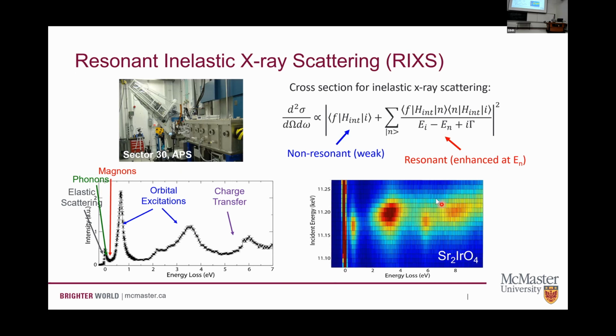Yeah, so that's the orbital selectivity that I mentioned. The difference here in energy along the vertical, which is as we're scanning the incident energy, that's 10 Dq. That's the difference between exciting your core electrons into the t2g levels, that's what you're getting here and here, versus going into the eg levels, that's what you're getting here and here. So that's really helpful when you're trying to identify what these orbital transitions are coming from.